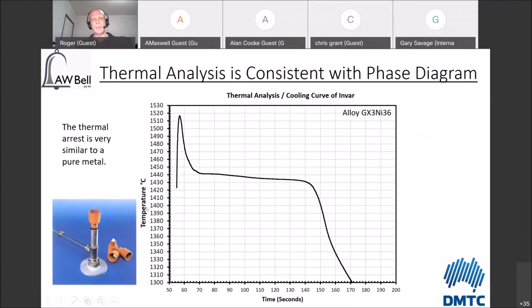So what you're seeing on the plot here is while it's heating up, and then when it reaches its maximum temperature, it starts cooling back down again. You can see that, probably because it's not purely iron and nickel, there is a little kick just before the start of the main thermal arrest. But it's very, very flat, quite consistent with something that is close to a pure material, but of course it's not pure because it's got very, very high alloying content in it.